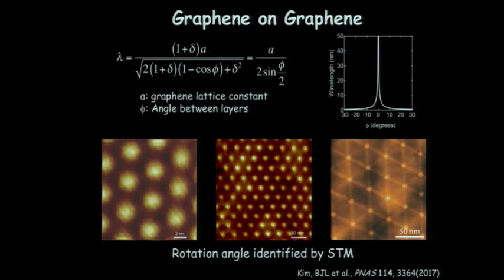And so here are some examples of Moiré patterns that we've measured in this twisted bilayer graphene case. So this is about a 5 nanometer Moiré. This one is on the order of 20 nanometers, and this one is on the order of about 50 nanometers for these Moirés. So this corresponds to something like 0.2 degree rotation angle. I think this one is about 0.6 or so degrees rotation angle. And so you can get these very long Moirés, something that's just not possible in the graphene on boron nitride case because you have the same lattice constants.